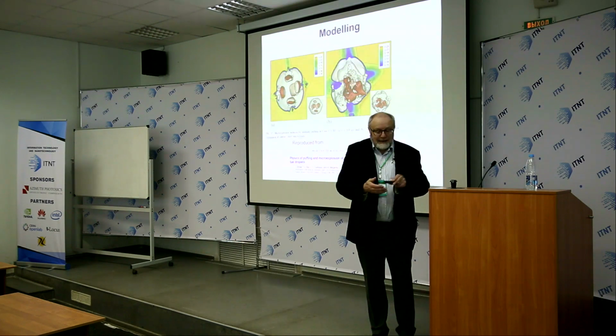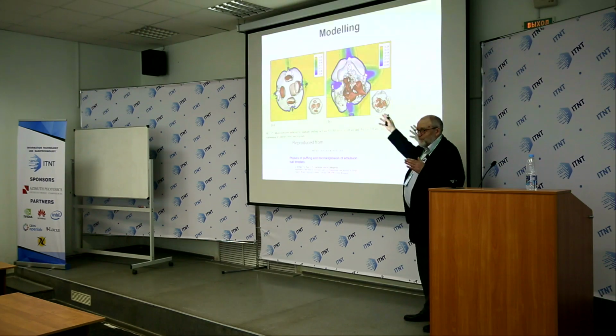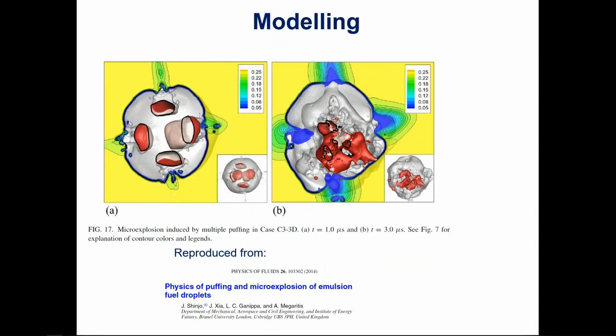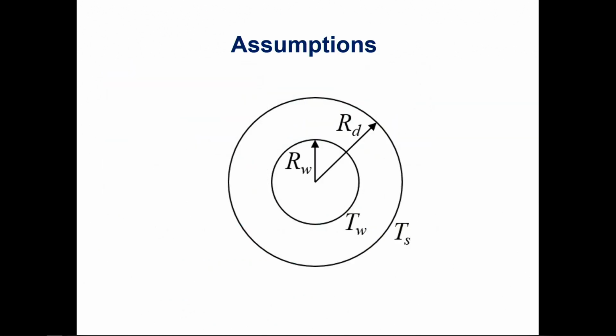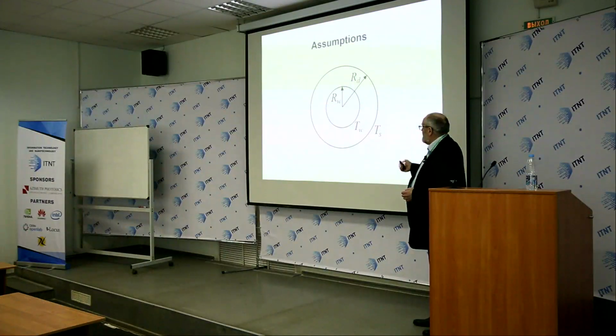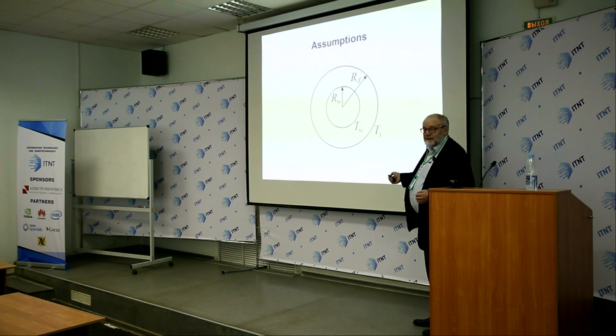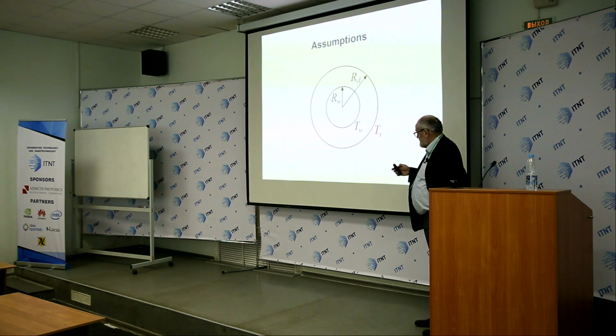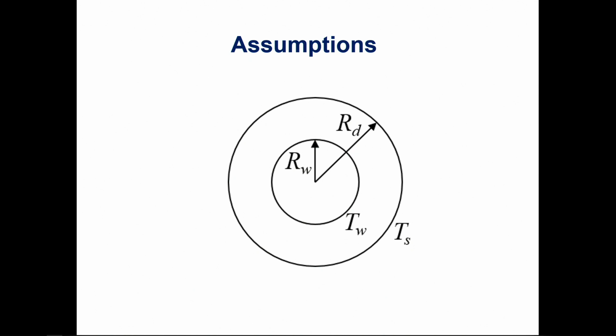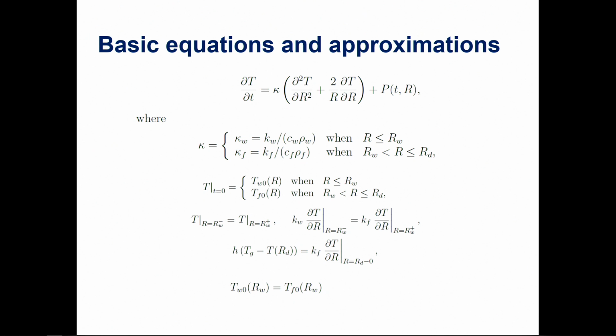So this led us not to try to compete with this group and develop a more sophisticated direct numerical simulation model, but to approach the problem from a completely different perspective. So what we did, we developed a very simple model. We considered that a water subdroplet of radius RW is located in the center of a big fuel droplet of radius RD. Then the temperature at the interface between water and fuel is TW, and the temperature at the surface of the fuel droplet is TS. And then we return to the same heat conduction equation inside the droplet.